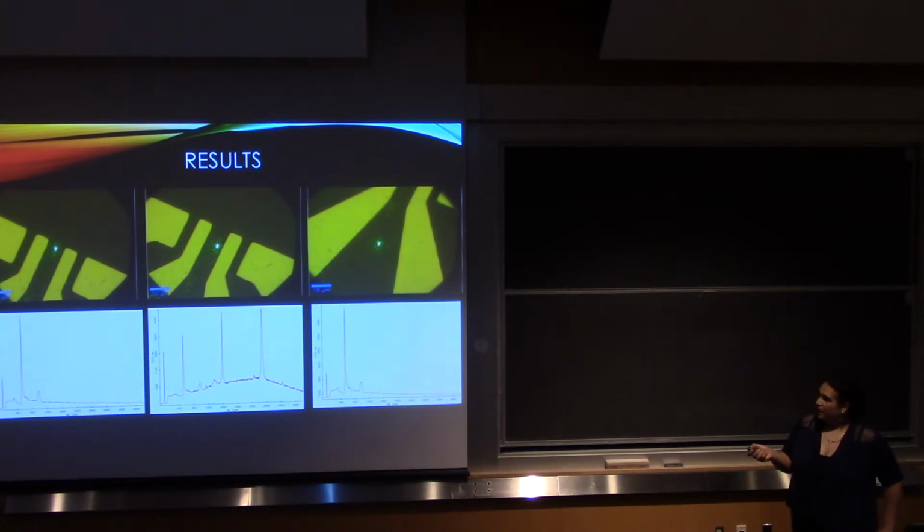So the one in the edge, where we didn't want graphene, as you see, has very little at the 1600 one, but none at the 2700. And the one in the middle, which we wanted to have graphene, as you see, has two very distinct peaks for both areas on the graph. As well as further down the line, we do not see any graphene peaks, in the 2700 and one, I think very little one here.